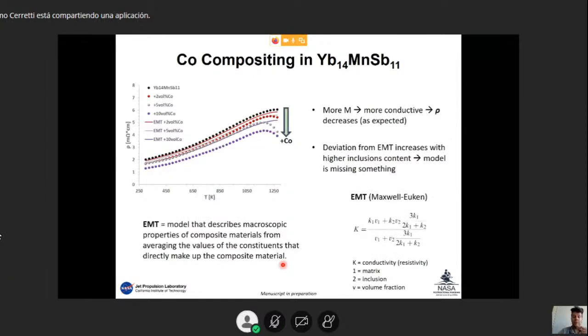So when we pass to characterize the materials, we observe that the more cobalt we put inside, the more conductive the material is, and that's as expected. So we have a decrease of the electrical resistivity.